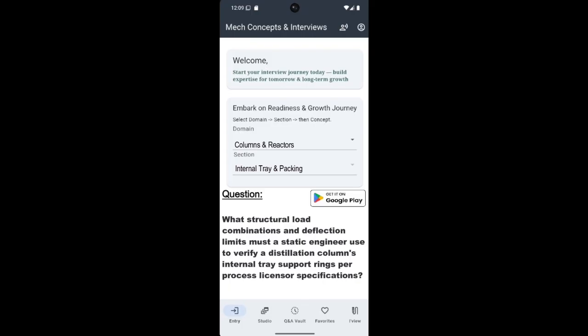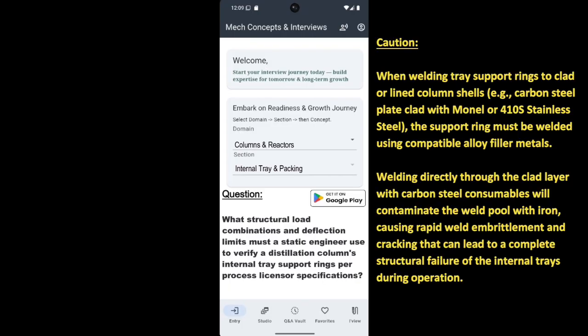I'm looking for a detailed metallurgical caution here. Distillation columns often utilize clad materials for economic corrosion resistance, a cheaper backing steel with a thin layer of high-grade alloy. How does this complicate the welding of your tray support rings? Significantly. When welding tray support rings to clad or lined column shells, for example, a carbon steel plate clad with Monel or 410S stainless steel, the support ring must be welded using highly compatible alloy filler metals.